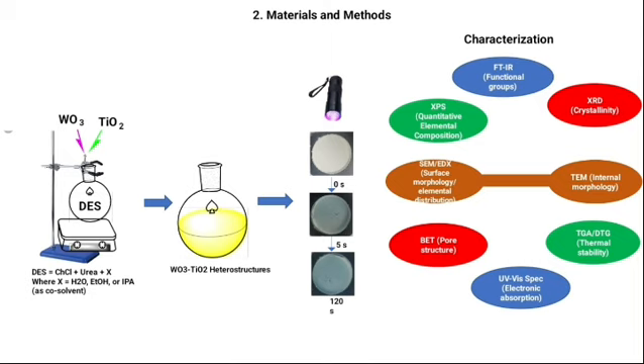Thereafter, 1.0 gram of tungsten salt was directly added to the solution, followed by 0.5 ml of titanium isopropoxide to give a colloidal solution. The mixture was allowed to heat and stir for 1 hour, after which 5 ml of glacial acetic acid was used to adjust the pH and give a clear solution containing tungsten oxide and titanium oxide heterostructures after the solution was heated for another 2 hours.